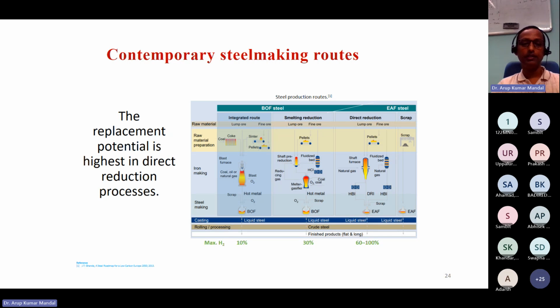If you see the iron making process, if you think about BOF steel making in the integrated steel plant route, in the iron making area hydrogen can be replaced only up to 10%. It means that 10% of conventional fuels can be replaced by hydrogen. Therefore, the integrated steel plant has less probability to use hydrogen. If you go for the smelting reduction route, you can replace up to 30% with hydrogen. But there is a probability of replacing the conventional fuel by hydrogen up to 100% if you go for the DRI route, the direct reduced iron route.